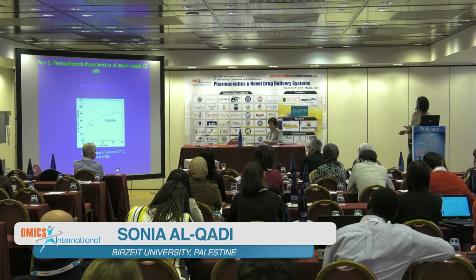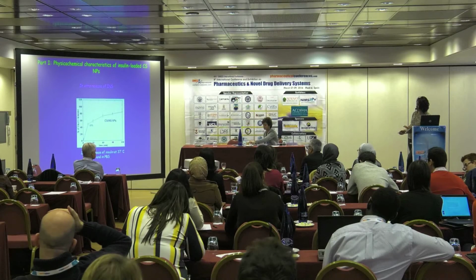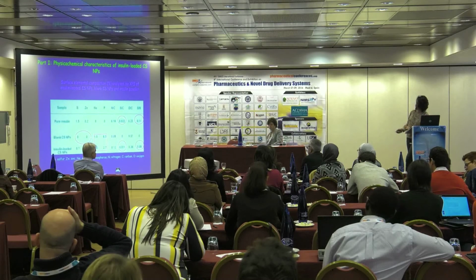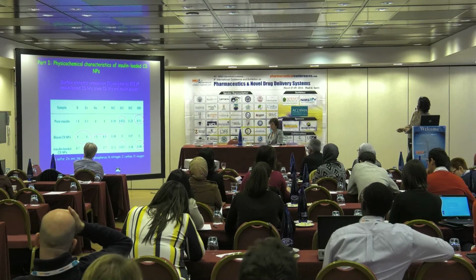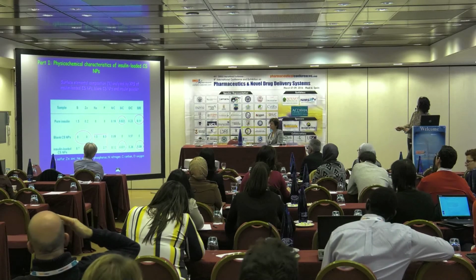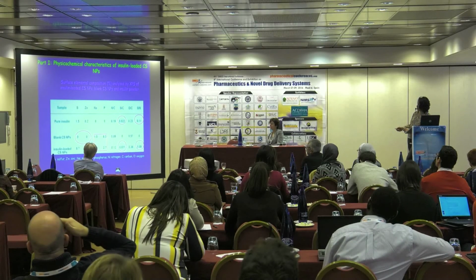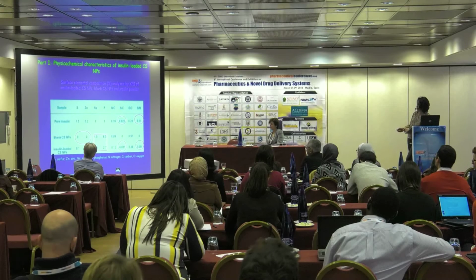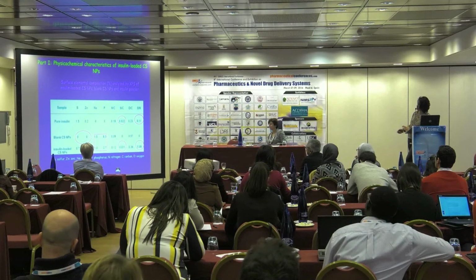So to make sure of this, we conducted further studies, including surface elemental analysis, where we used X-ray photoelectron spectroscopy to check if we have a proportion of insulin adsorbed on the surface of the nanoparticles, which would be responsible for the burst release.